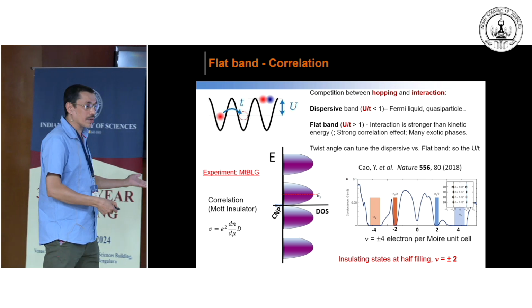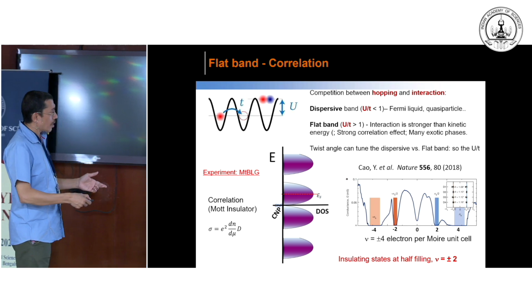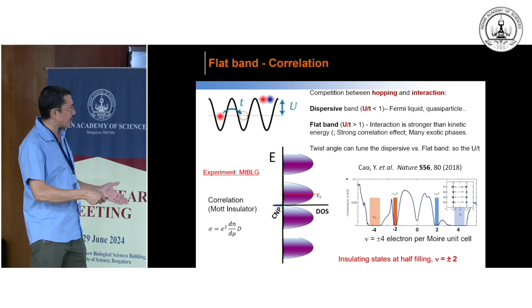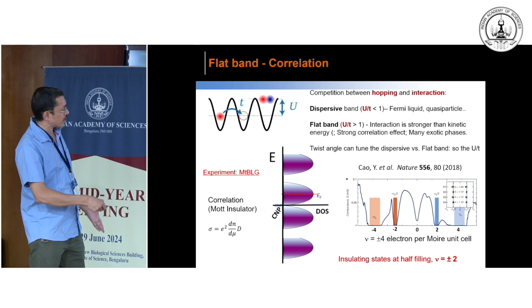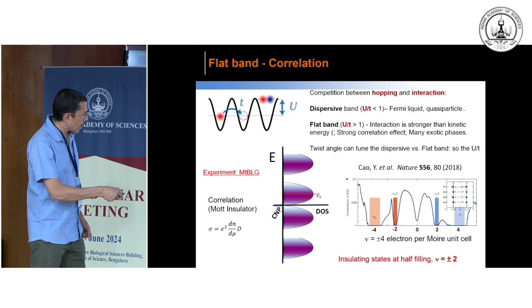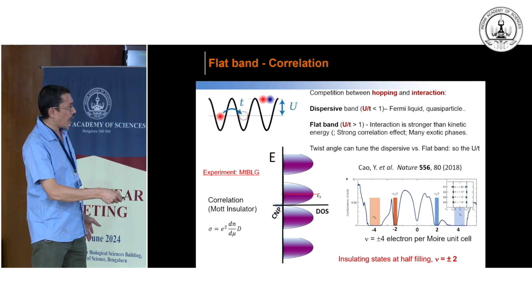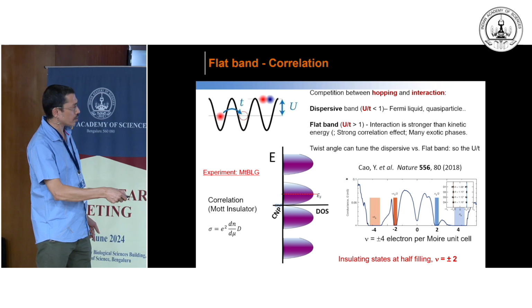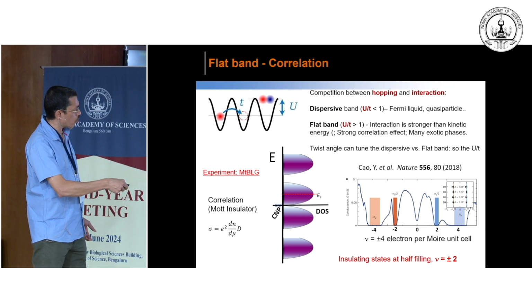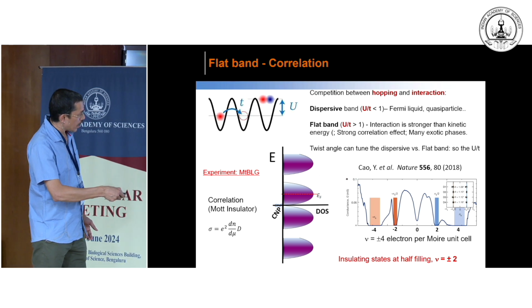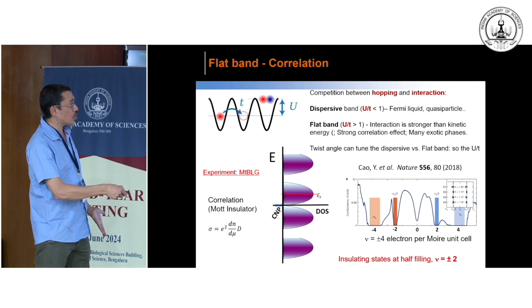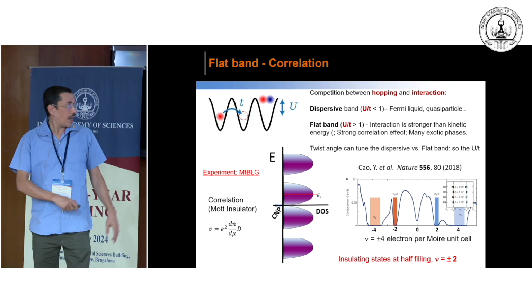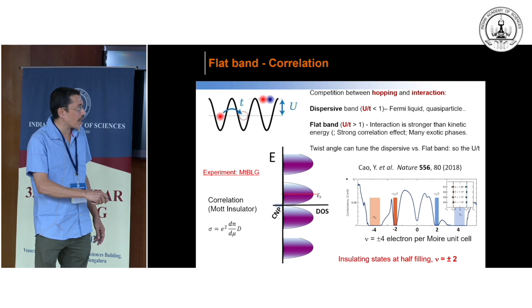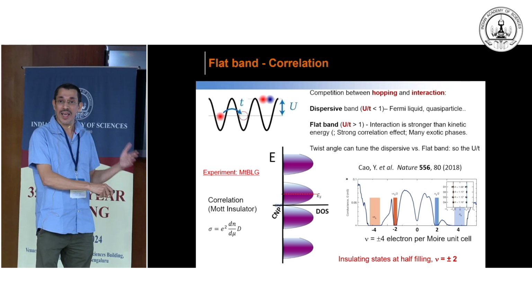That's the way this field started. Although MacDonald predicted it in 2011, the first paper came out in 2018, and they saw an unusual result. This is a cartoon picture of the density of states of your twisted bilayer, but they saw many features in the conductance. First of all, at the Dirac point you have a low density of states, so your conductance is very low. Then you have this Moire gap, which our previous speaker already mentioned, because of the zone folding, and again conductance goes to 0 because there are no states. However, even when the Fermi energy is inside the band, where you should have a large density of states, the conductance goes to 0. That is the remarkable result: you are inside the band where the single particle density of states should have been maximum, but your conductance goes to 0.